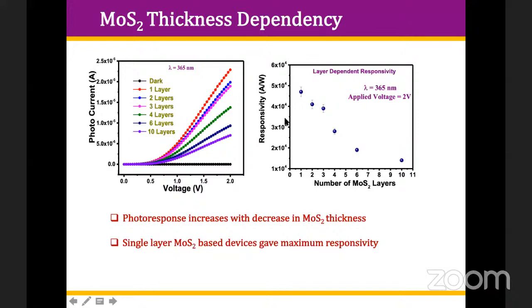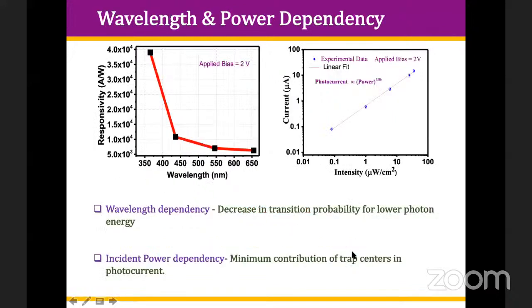So the UV detector is good if your layer is small. So monolayer, you can say, is the preferred one to make the photo detector. Single layer MoS2 based device gives the maximum responsivity in the system. We applied different lights, different wavelengths, and we found that the lower wavelength, higher energy gives the better responsivity as compared to the higher wavelength or lower energy.